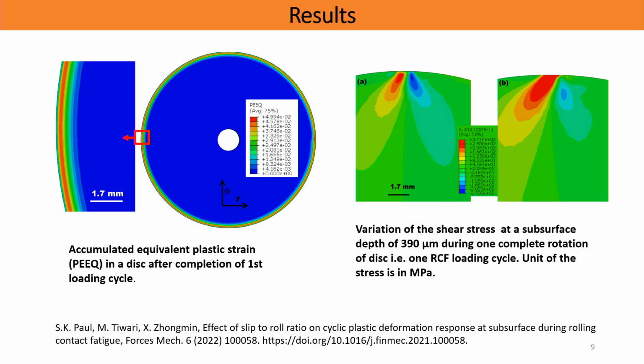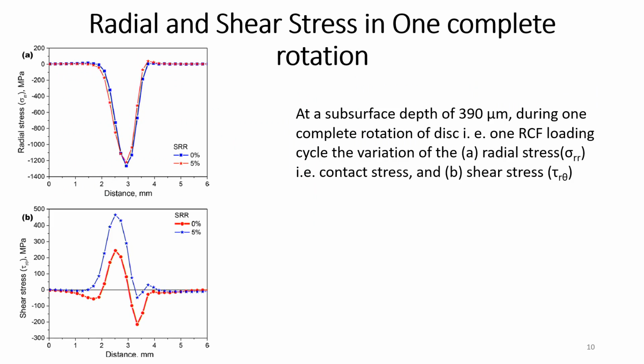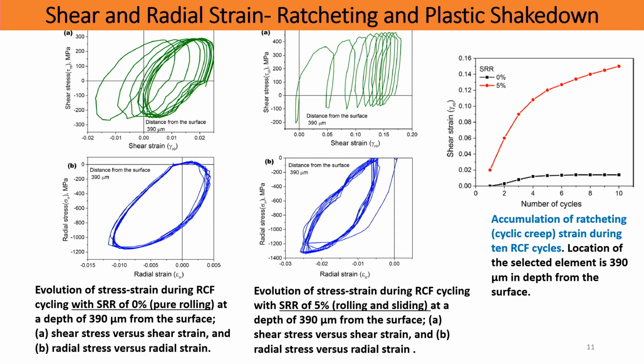Okay. But this is an Abaqus modeling we've done. So this also shows the symmetry: symmetry is not there at 5%, blue, and symmetry is there in red, which is 0%. Now what we see from this is that there is what is called ratcheting happening when you include slide. Okay, this is the accumulation of the plastic strain which goes on increasing like this, red, if you have sliding, and if there is no sliding, this ratcheting doesn't happen. It's called plastic shakedown. So this is one takeaway from this study we've done.